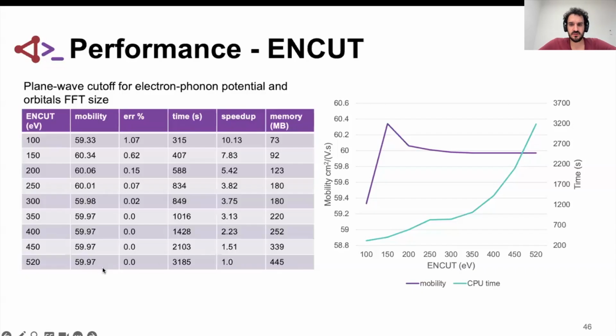As we can see in this calculation, even using a very low cutoff of 150 EV, we are still only making an error below 1%. If we compare the computational time, here it takes 400 seconds, while if we used a safe value of 520 EV, it would take 3,000 seconds. So it is quite a significant speed up — we're talking about 8 times speed up, and also a significant reduction in the amount of memory required.